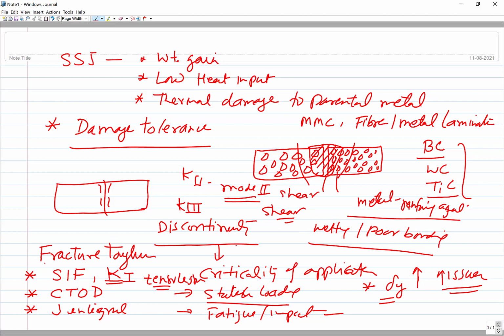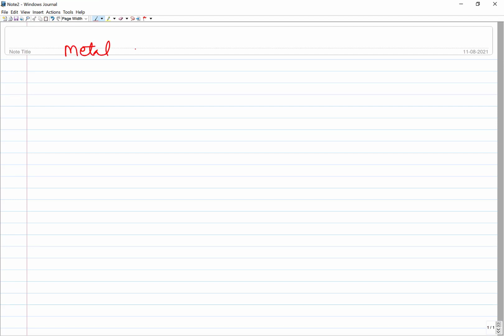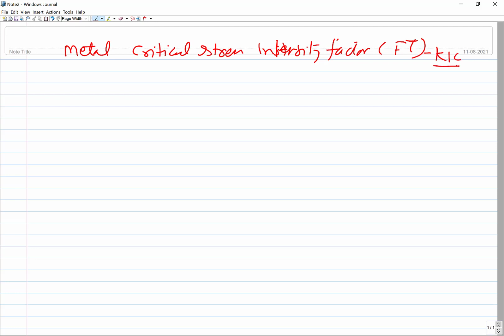So the most common fracture toughness parameter is K1. This is the stress intensity factor for a metal, but when we have to use it for design purposes, a particular metal will show its critical stress intensity factor. This is one of the parameters of fracture toughness, represented by K1C, and this is basically a metal property, just like yield strength, used for design purposes. Similarly the K1C is also quantified.